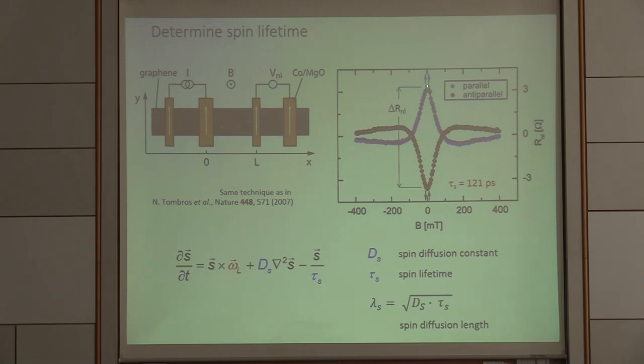So you see I'm injecting in this direction. This is the magnetization. And then my spin actually can precess in this B field. And now that's exactly this curve which you see here. So here we plot again this non-local resistance. What I showed you before was a different device. Before we had here eight ohms, now we have three ohms. But it doesn't really matter. Here, this is now parallel configuration. If I start now switching on the out-of-plane magnetic field, my spins are precessing. And this resistance goes down.